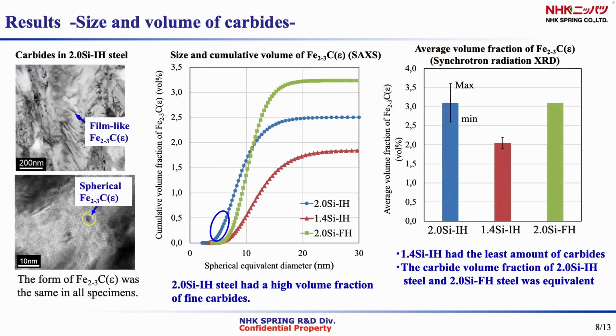This picture shows the carbides in 2-silicon IH steel. Most of the carbides were epsilon carbide, not cementite. The morphology of epsilon carbide was mostly lath-like, but some spherical carbides were also present. The form of epsilon carbide was the same in all specimens.